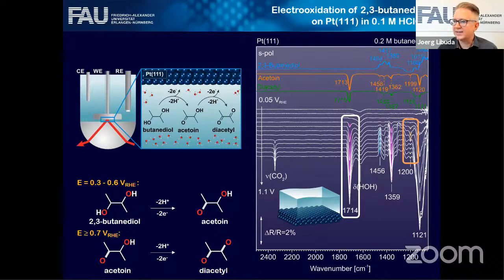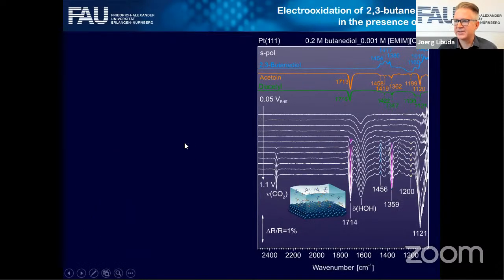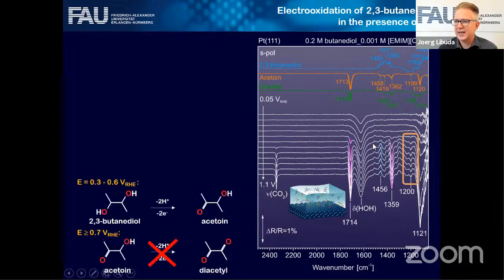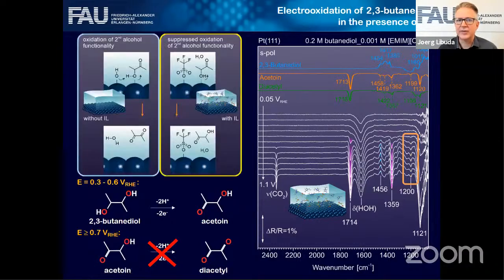Now we do exactly the same thing in the presence of the ionic liquid. So we follow the same two bands, and now we see something completely different. We see that we make the acetoin, but then the reaction stops. So we selectively oxidize to the acetoin, but the second reaction, the full oxidation to the diacetyl, stops. So why is that? We believe that this is the effect of this ionic liquid, of the OTF anion.